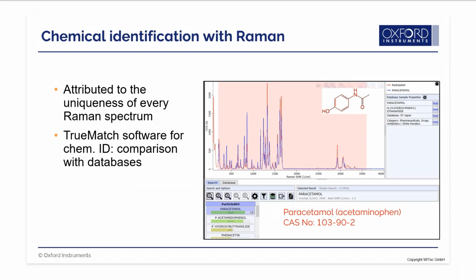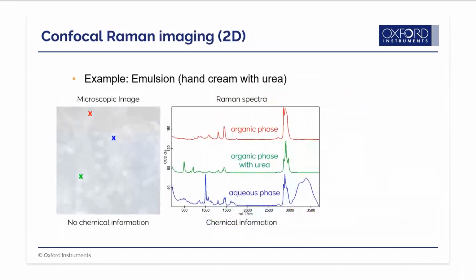TrueMatch also offers the possibility to build a database from own reference samples. Beside identification, it is also important to obtain information about the distribution of materials. On the left, you see the microscopic image of an emulsion containing urea. Spectra measured at 3 positions of the sample reveal various organic phases. In red, an oily phase, in green, the phase containing urea, and in blue, an aqueous phase.